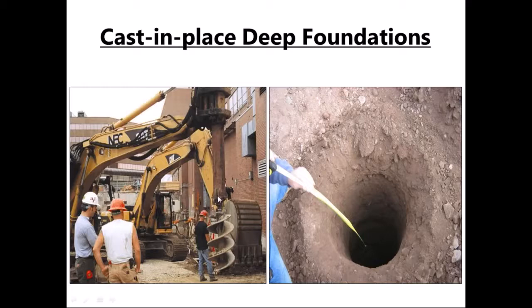So with the cast in place elements, there's typically an auger or some sort of casing and drill bit that will create a void down to a certain depth. And then that void is going to be filled with concrete or grout material. And then sometimes for the larger drilled piers, there may be some rebar cages that are placed that will require some reinforcing steel inspection.